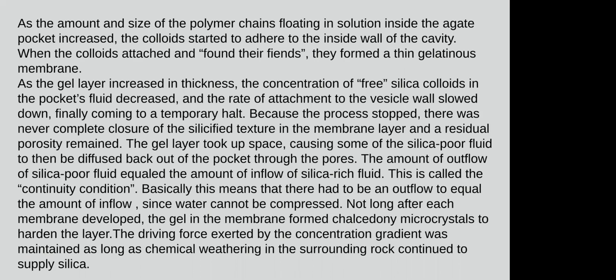The amount of outflow of silica-poor fluid equaled the amount of inflow of silica-rich fluid. This is called the continuity condition. Basically, that means there had to be an outflow to equal the amount of inflow, since water cannot be compressed. Not long after each membrane developed, the gel in the membrane formed microcrystals to harden the layer. The driving force exerted by the concentration gradient was maintained as long as chemical weathering in the surrounding rock continued to supply silica.